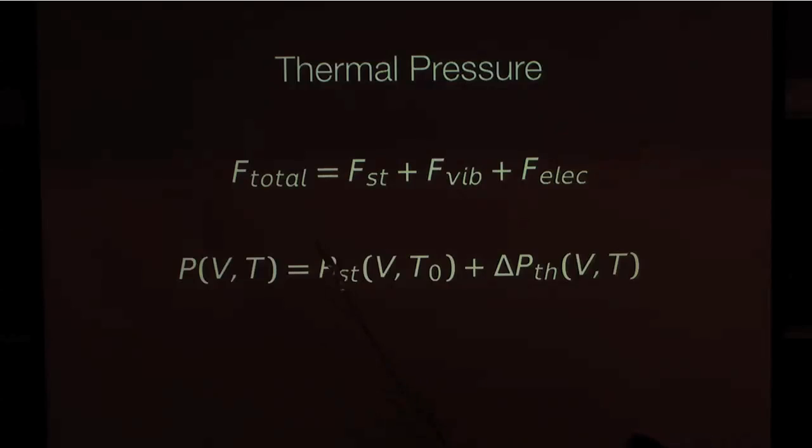And if you take the first partial derivative of this equation with respect to volume, if you remember those thermodynamic relations, you come up with pressure relations, right? So this relation directly comes from this relation by just taking the partial derivative of this one with respect to volume. If you take constant entropy, then you will get the adiabatic equation of state. If you take constant temperature, you get isothermal.